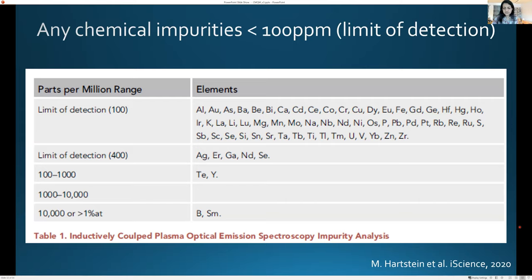We also are very careful to do optical emission spectroscopy, which is a bulk measurement of the material, to put a bound on any impurities. And the method is able to put a bound at the limit of detection of almost all possible inclusions, and up to the limit of detection of everything, the rare earths are below 400 ppm or even below that. This is just the limit of detection. And so one can see clearly from here, there's no evidence for any inclusion, certainly not at the level at which one would see large Fermi surfaces.